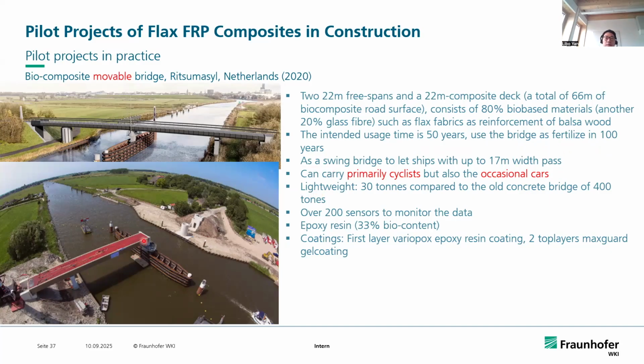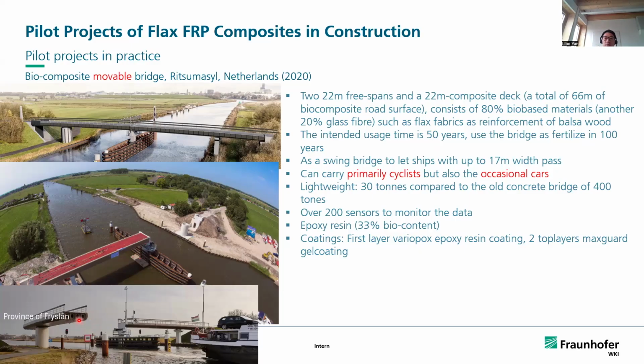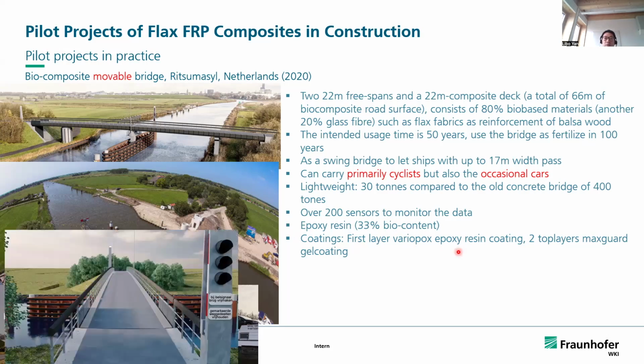This bridge also allows ships to pass by, up to 17 meters wide. It is mainly designed to carry cyclists, but also occasional car transportation. Compared with the older concrete bridge of 400 tons, the composite bridge is about 30 tons, which is reduced significantly. Over 200 sensors were implemented to monitor the long-term performance. And of course, coatings are used to prolong the durability of the flax fiber reinforced polymer composites. Here you can see the road surface of the composite deck.